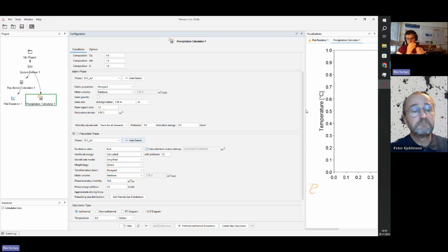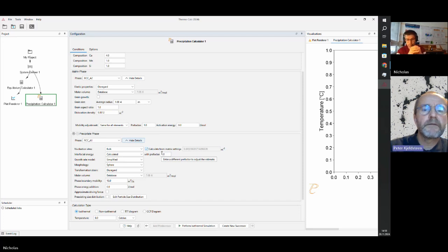So you've got the uncertainty in the nucleation models. And how nucleation and growth actually works is it generates new interfacial area that slows down the growth, right? And you've got a thermodynamic driving force that drives the growth. And this interfacial energy has quite a high uncertainty. We have a model to calculate it, but it's just something that's hard to calculate. So we're starting to pile up the uncertainties here. But let's see how we get along.